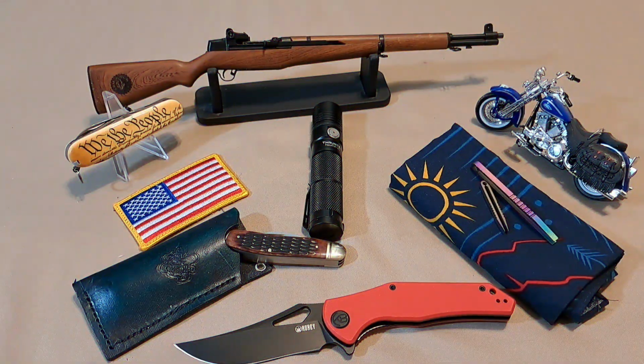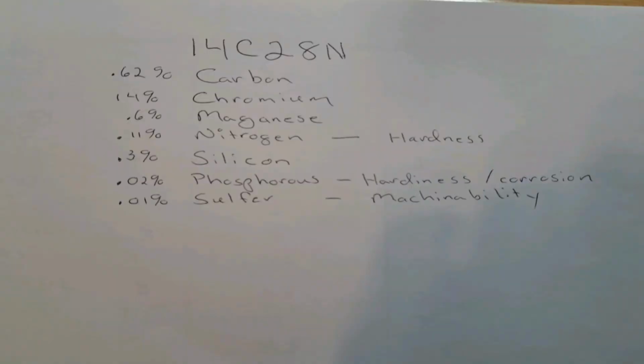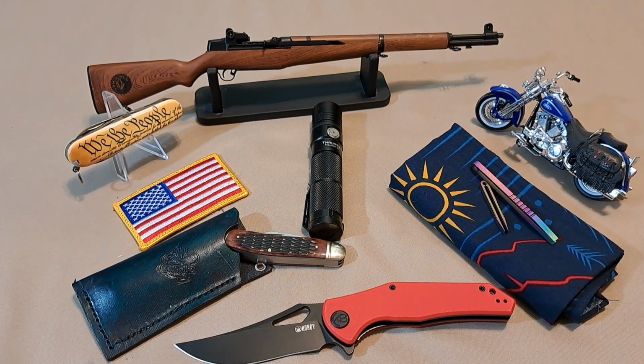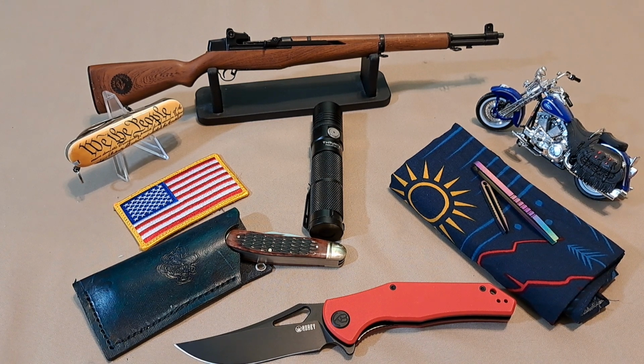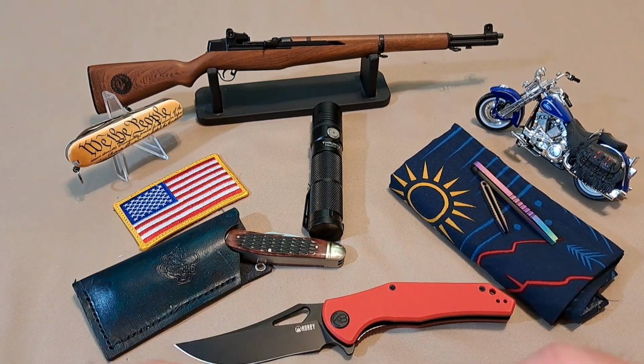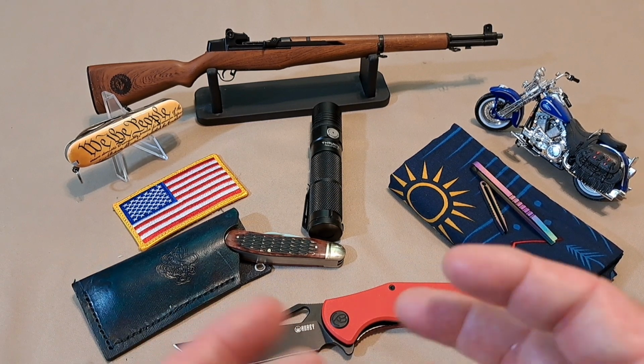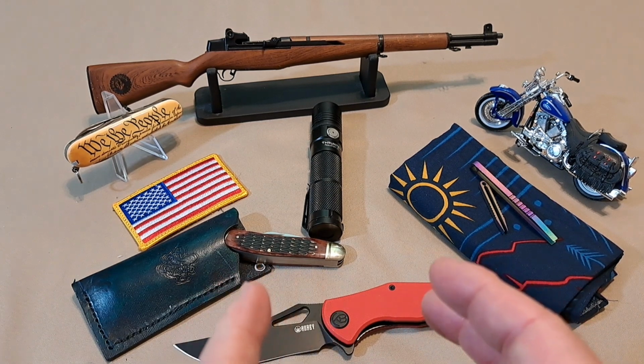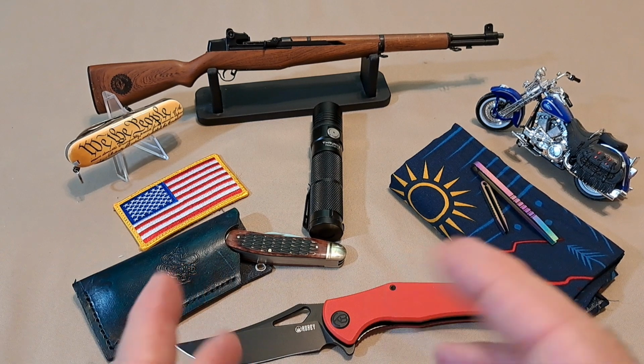All right, so you're looking at the chemical composition right now. It has 0.62% carbon, 14% chromium, so it is a stainless steel. It has 0.6 manganese, 0.11 nitrogen, 0.3 silicon, 0.02 phosphorus, 0.01 sulfur. Usually sulfur and phosphorus are considered contaminants in steel, but this is a very clean steel. Swiss steel is known for its purity. When you add those ingredients in a measured way, they actually contribute to the steel. Phosphorus will make the steel harder and more corrosion resistant, and sulfur adds to the machinability, which is one of the reasons why this steel is easy to work with.